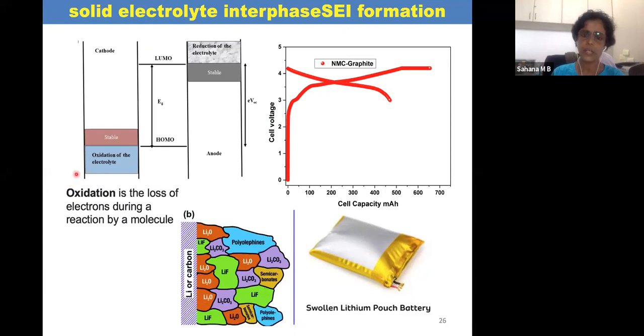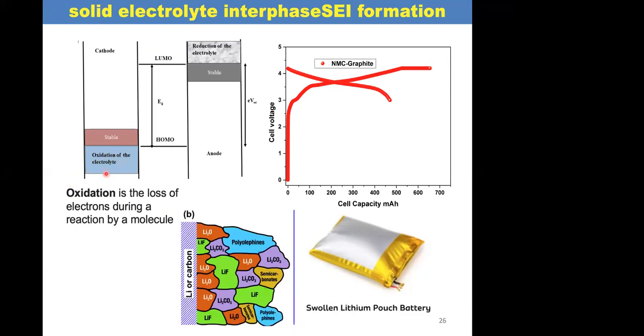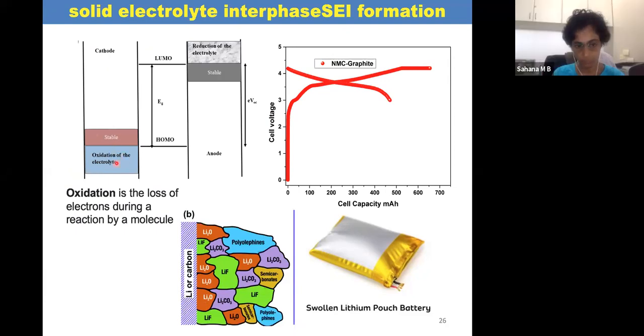Similarly, if the decomposition happens on the cathode side also, a stable layer forms on the cathode side. Now these SEI layers are electronic insulators. So they basically stop the further decomposition of the electrolyte solvents, but they allow the lithium to transport. This is what we require.